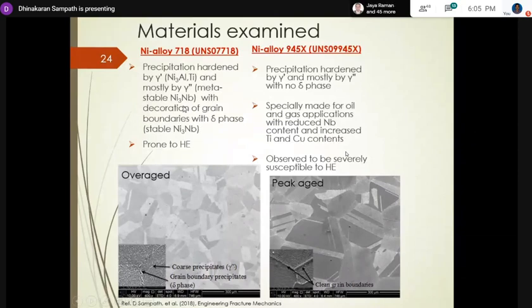Why? Because some of this gamma double prime is metastable, and it transforms into delta phase, which decorates the grain boundaries. A lot of these grain boundaries have delta phase, and when hydrogen goes there, it promotes a combination of mechanisms: decohesion as well as localized plasticity, and leads to intergranular cracking. So they are prone to hydrogen embrittlement, but still it's better than 725.